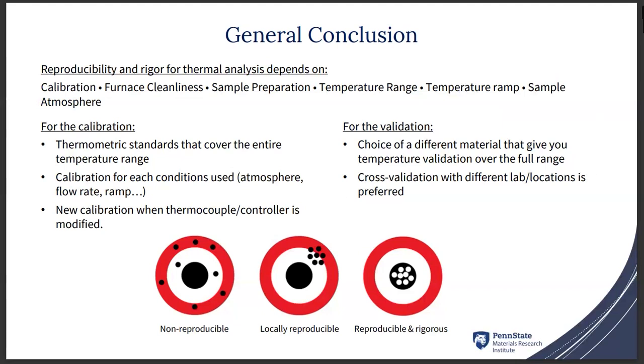For the validation, this is extremely important. You need to choose a material that gives you a temperature validation over the range, something that changes over time, which is what the magnesium stabilized aluminum titanate was used for.